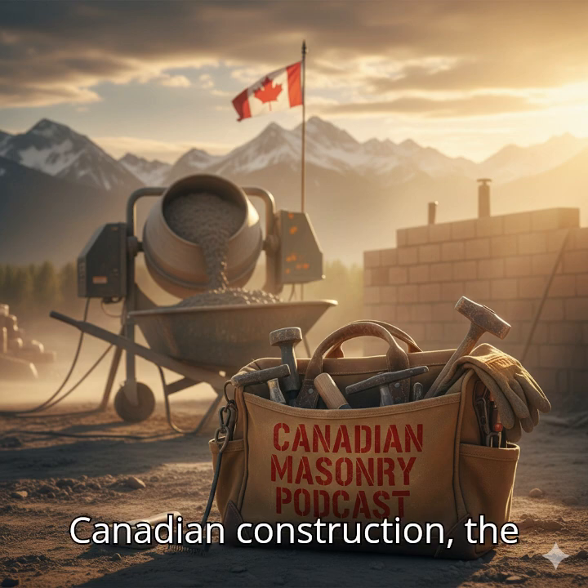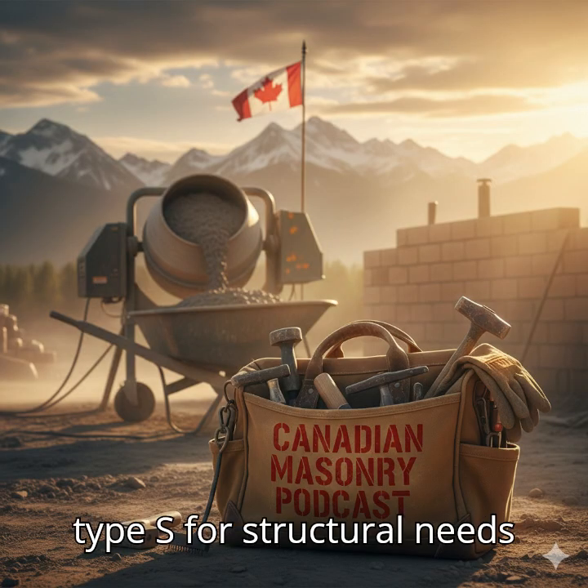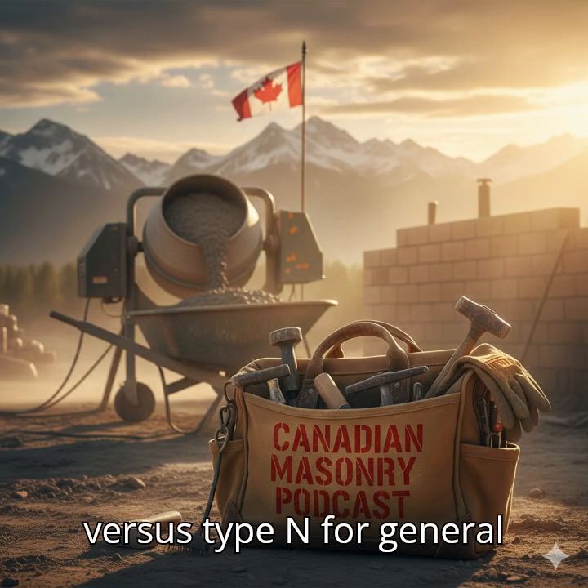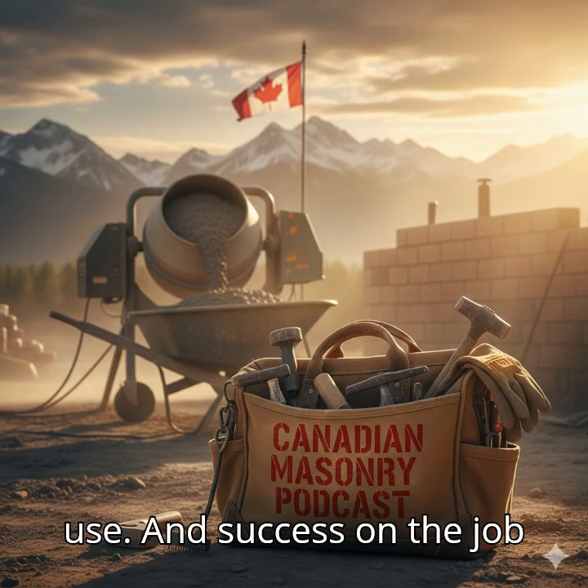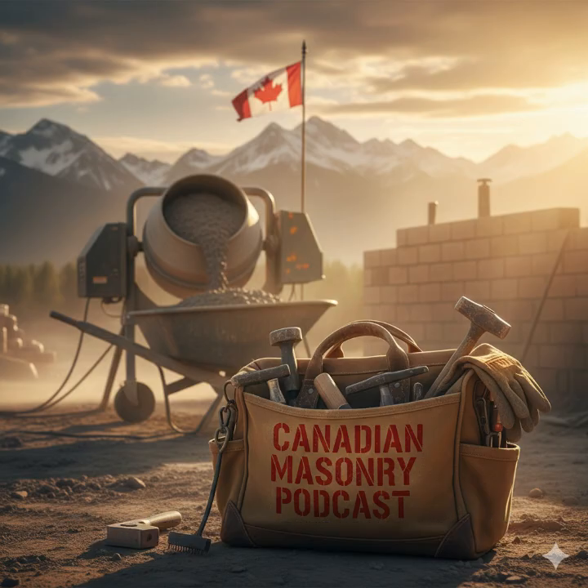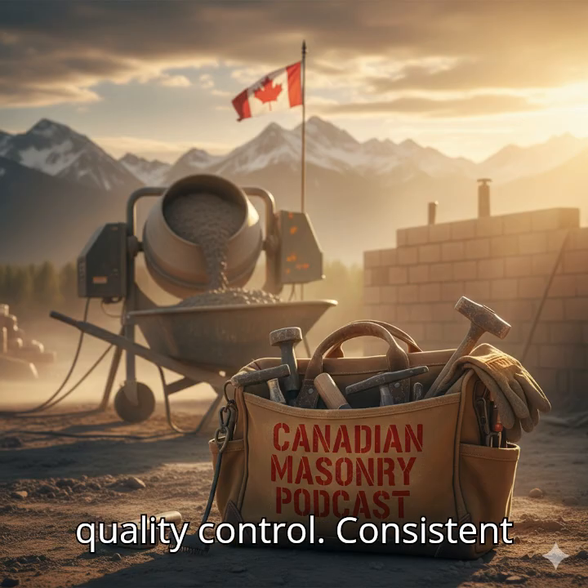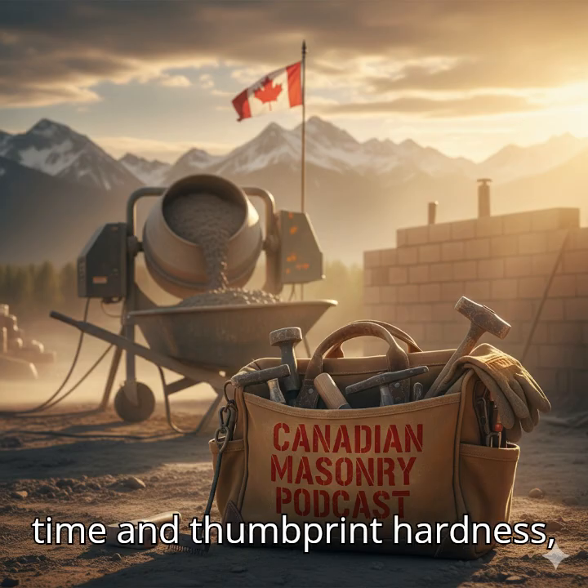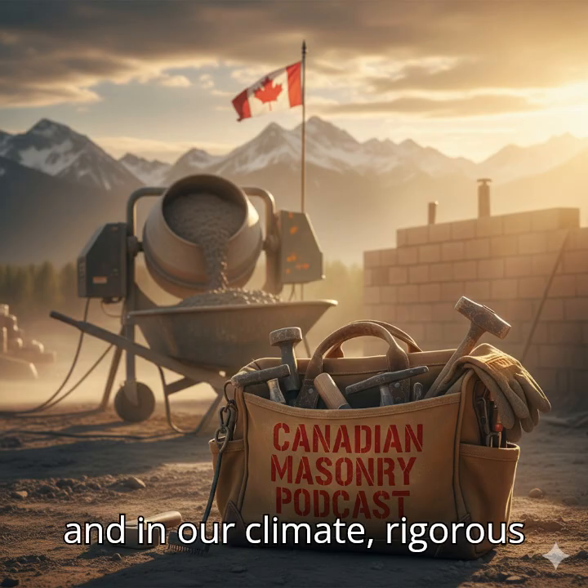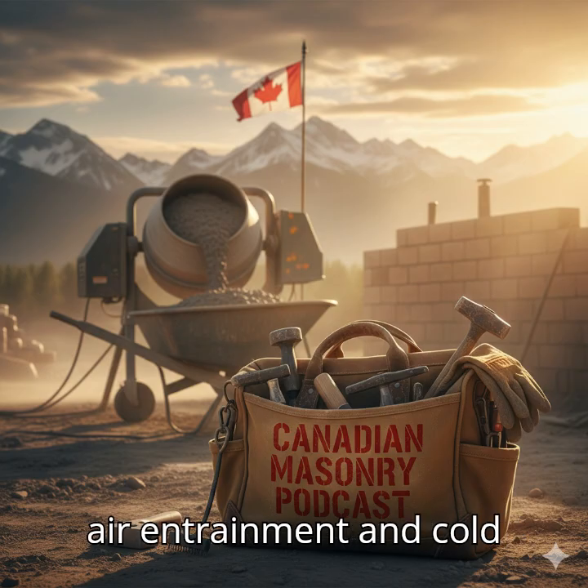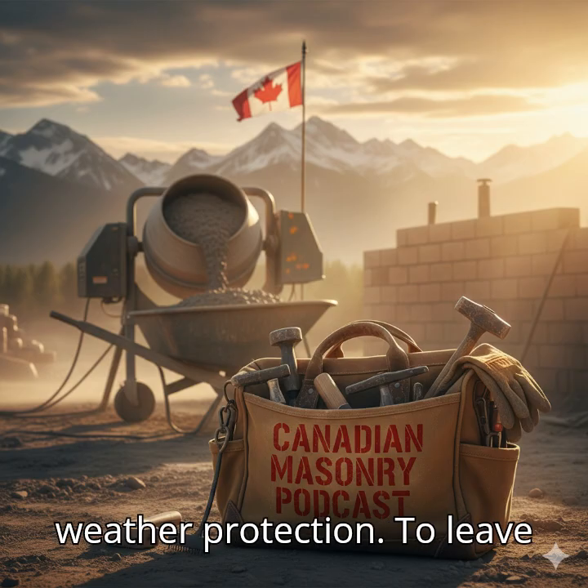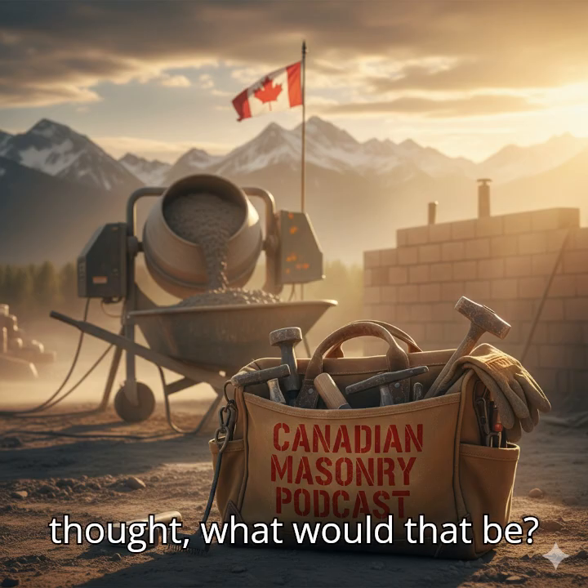And for modern Canadian construction, the choice really boils down to type S for structural needs versus type N for general use. And success on the job site comes down to absolute quality control. Consistent materials, perfect tooling time at thumbprint hardness, and in our climate, rigorous air entrainment and cold weather protection. To leave our listeners with a final thought, what would that be?